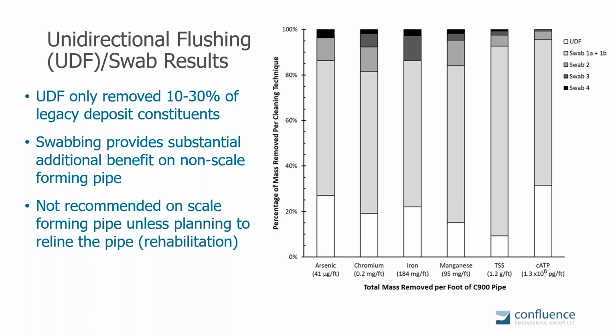Swabbing, the first pass of the swab provides substantial additional benefit to remove this material. I want to emphasize we don't necessarily recommend swabbing on a scale-forming pipe. Remember, that's with all the corrosion tubercles. This is on non-scale-forming pipe where you can safely squeegee the pipes without damaging the pipe or the corrosion scales.